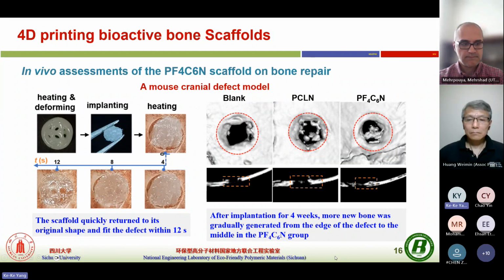After implantation for 4 weeks, we found that more bone was generated from the edge of the defect toward the middle, showing much better bone repair effects compared with the blank control.